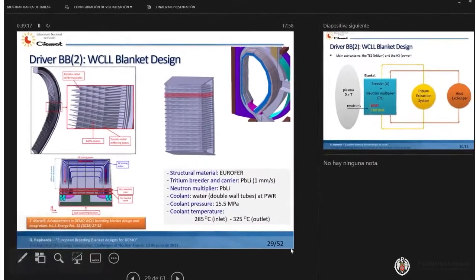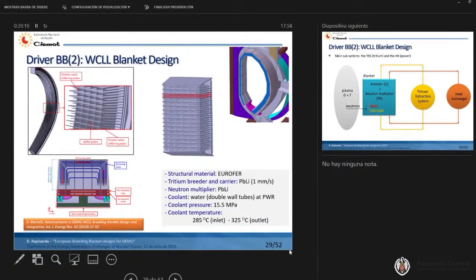In this case, the lead-lithium, you can see here the blanket. Remember that this is the torus of the machine. This is the blanket. The lead-lithium flows vertically, covering all these plates, in this direction. And the water flows in, this is a cross-section in this part, at this level. And in this cross-section, you can see the disposition of the different tubes with the water. The concentration close to this part, which is closer to the plasma, is because the neutrons impact more in this part, so there is more heat here, and we have to extract this heat, and for that reason we have more tubes. It's quite simple.